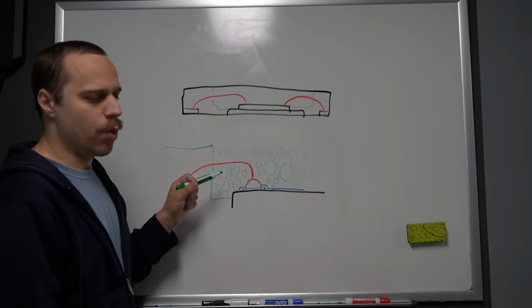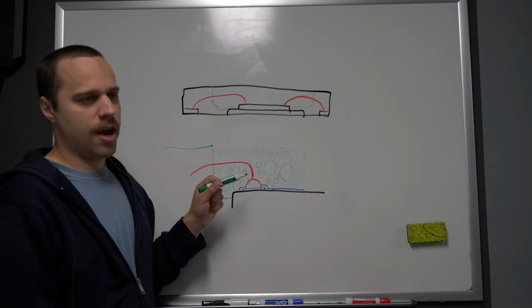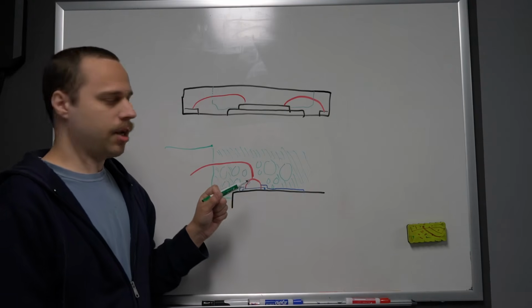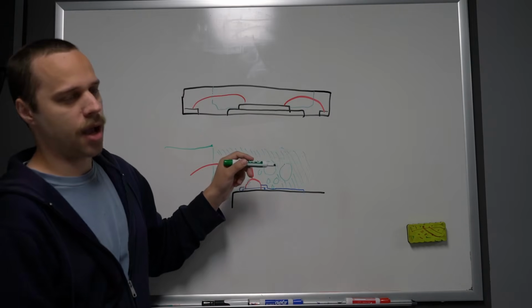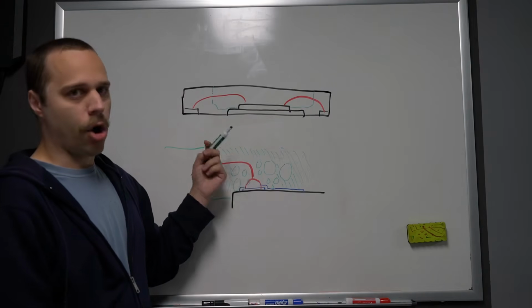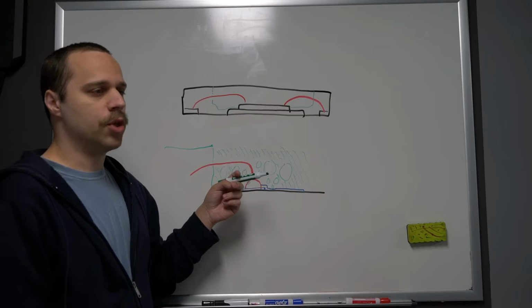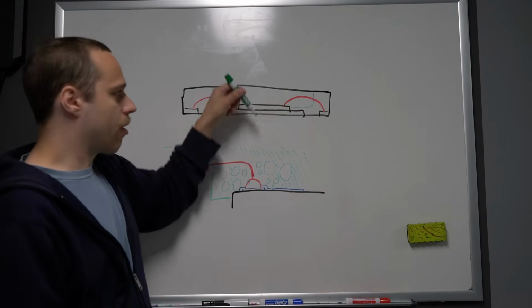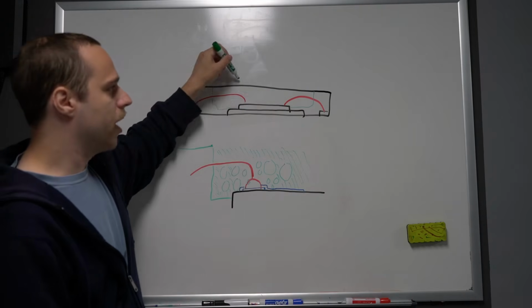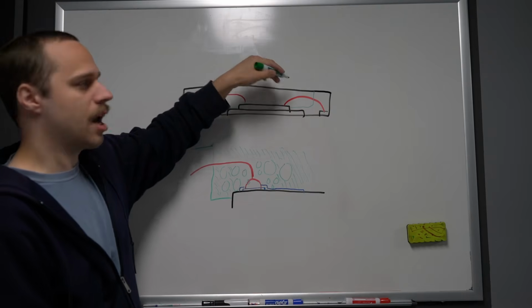So this requires that we use an etching technique that is both chemically and physically selective. We can achieve physical selectivity by a couple of methods. On larger devices like QFPs, you can just drop acid onto the center of the package. It's going to spread out a little bit, surface tension is going to hold it in place, and you get kind of a crater.